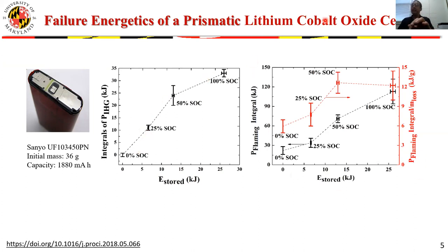Now, on the right-hand side, you see the graph that indicates heat generation due to the flaming combustion. So this is due to complete or nearly complete combustion of the organics that is ejected from the cell. And I guess it has more or less linear dependence on the energy stored as well. And if you look at the magnitude of that heat, it's about a factor of two larger than the magnitude of the heat release due to the thermal runaway reaction between materials.